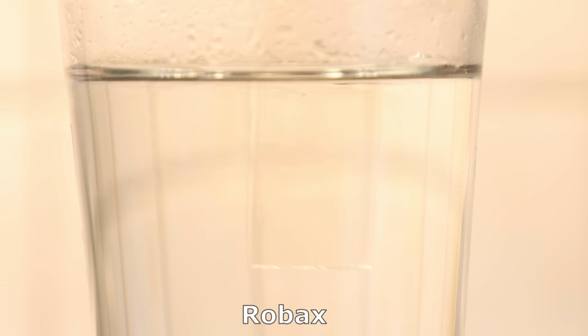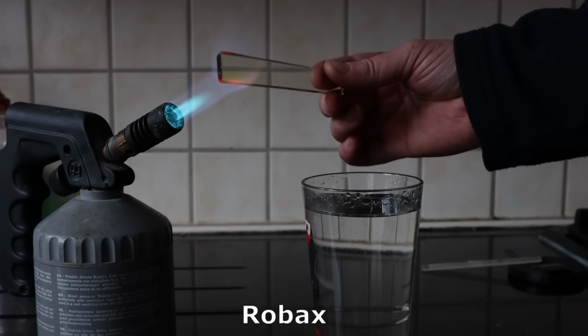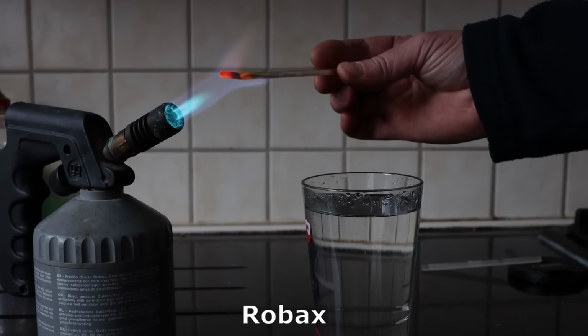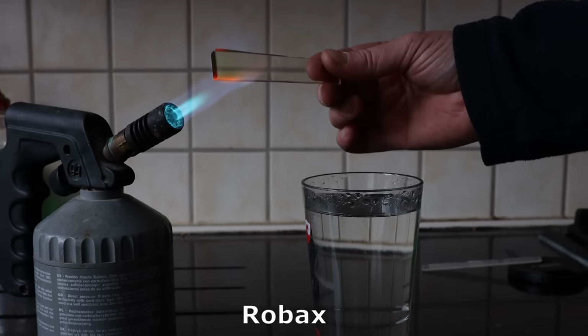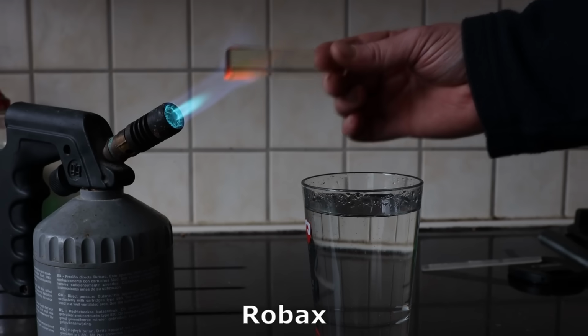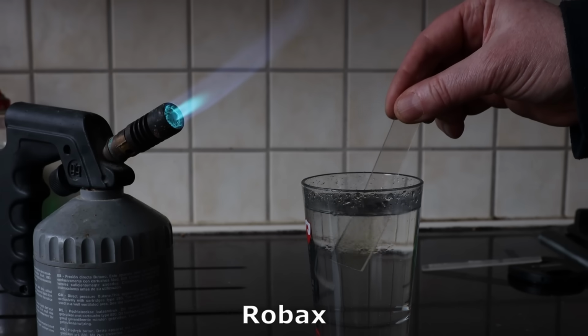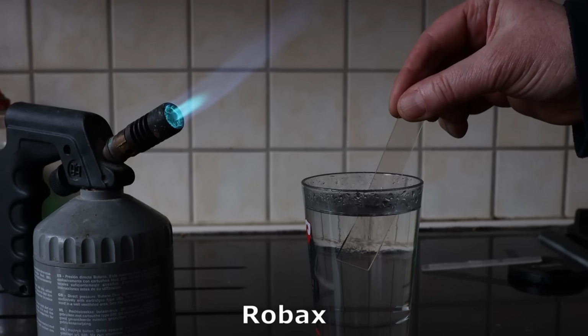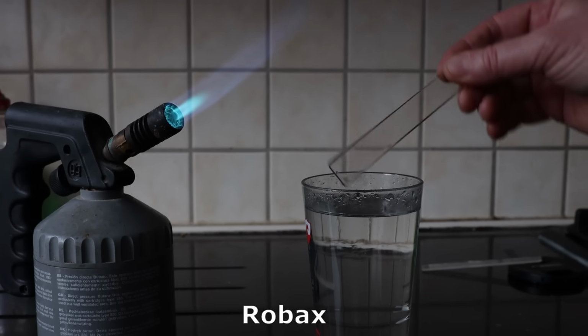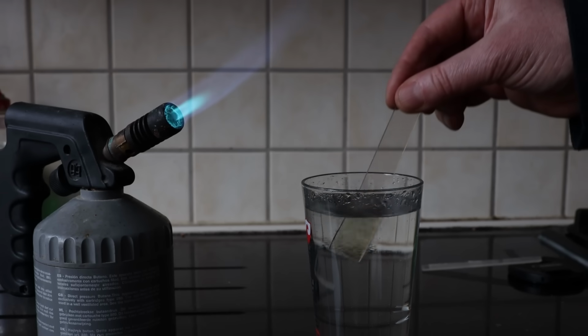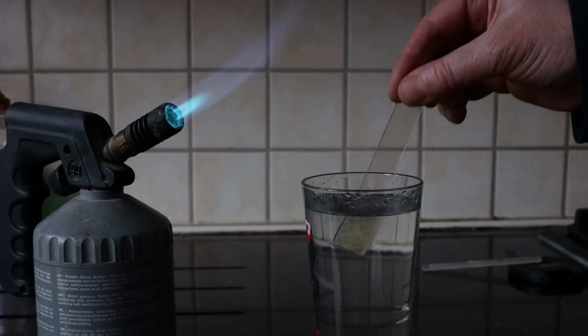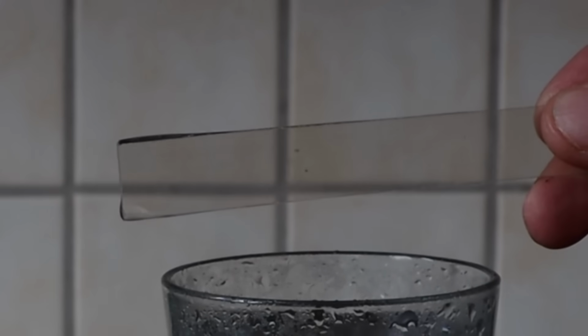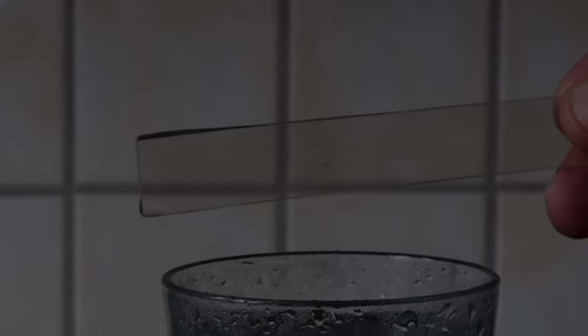We can make it quite a bit more challenging and heat the sample until it's red hot, meaning that the temperature is likely over 600 degrees Celsius. But even then, the thermal shock introduced by cooling down to about 10 degrees Celsius in only a few seconds does not pose a problem to this material. And you can repeat this procedure 1,000 times and nothing will happen. Now personally, I think this is totally amazing and it illustrates the remarkable thermal properties that some glass ceramics have.